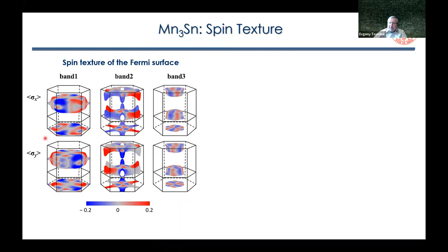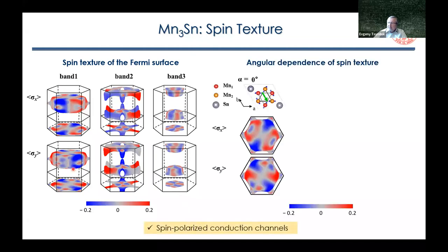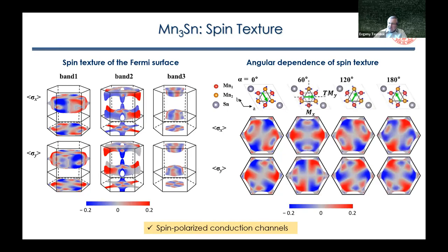So let us consider, for example, band one. This Fermi surface sheet is shown here on the left. If you look at the projection of this Fermi surface onto the 001 plane, you see that the spin components change from red to blue in a complicated way, different for the X and Y components. Similar to the band structure, if you now start rotation of the Néel vector, there is a rotation and it changes the shape and distribution of the X and Y components of the spin.